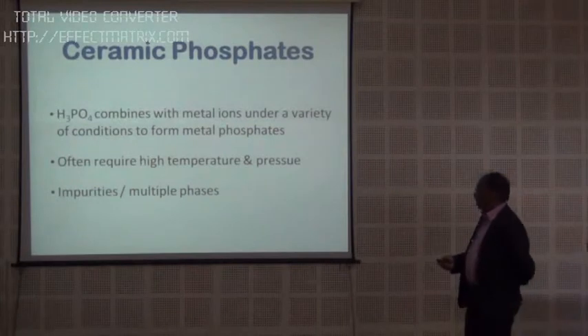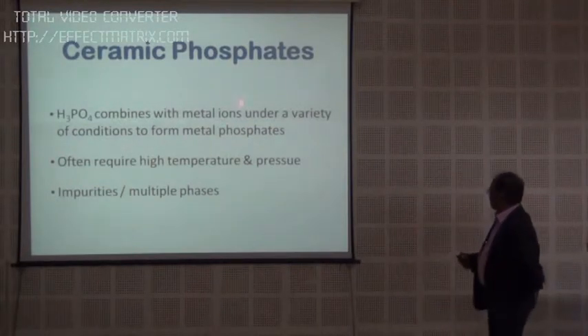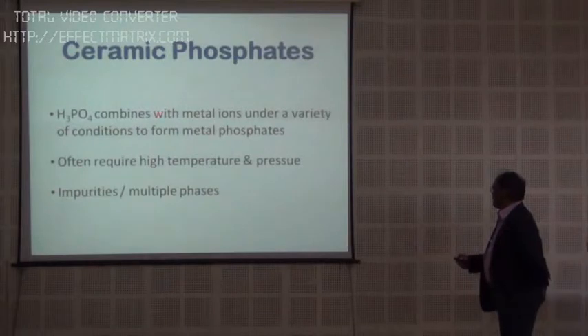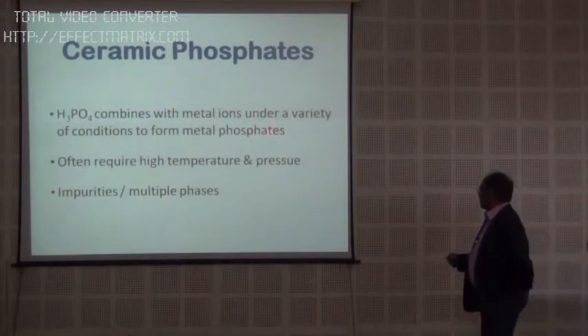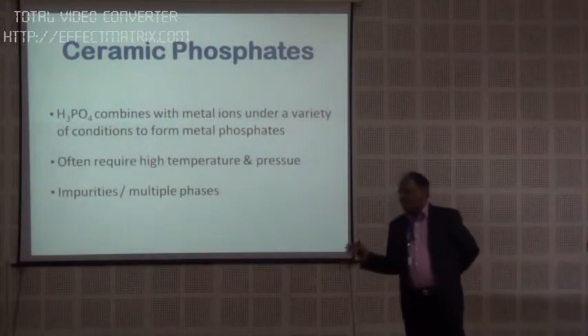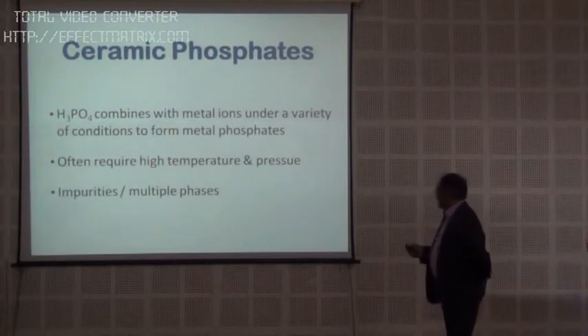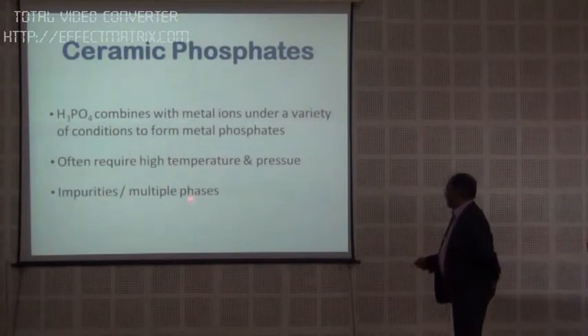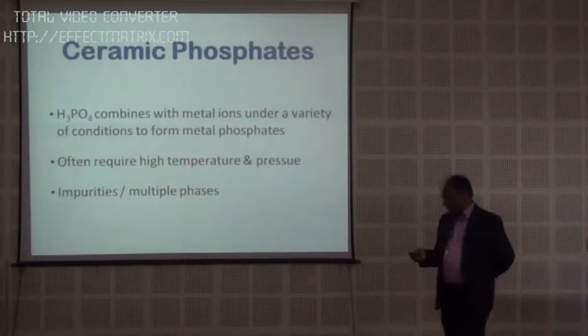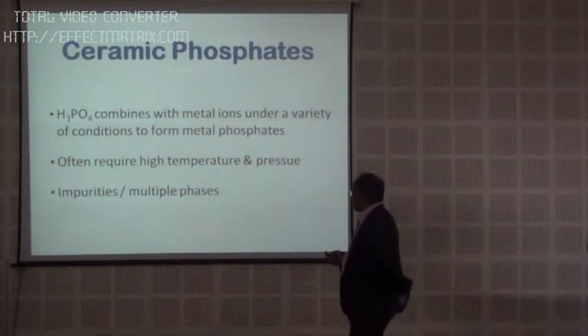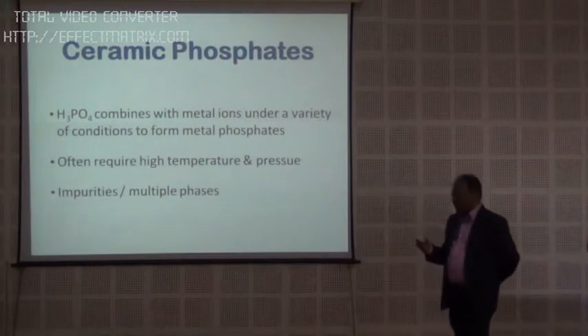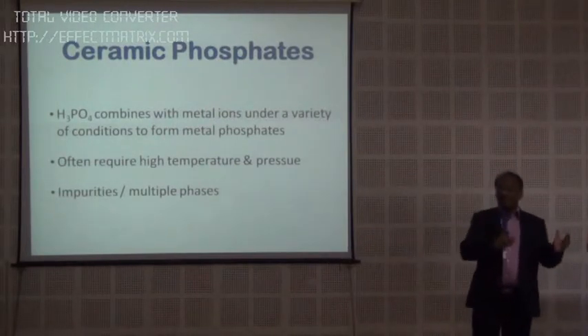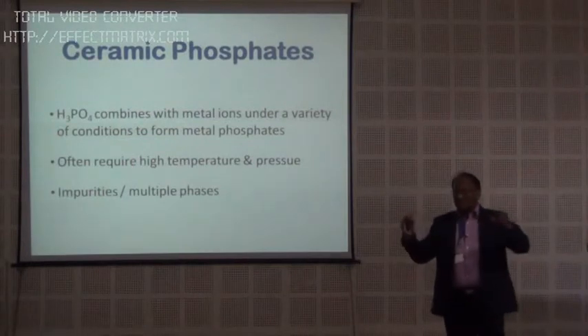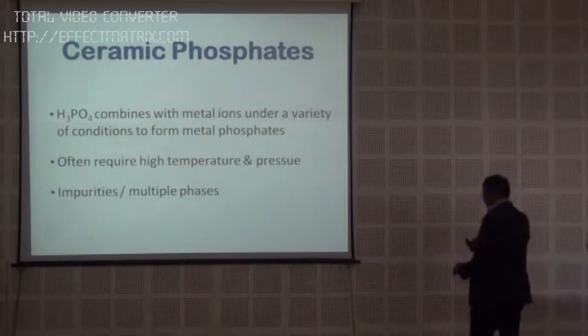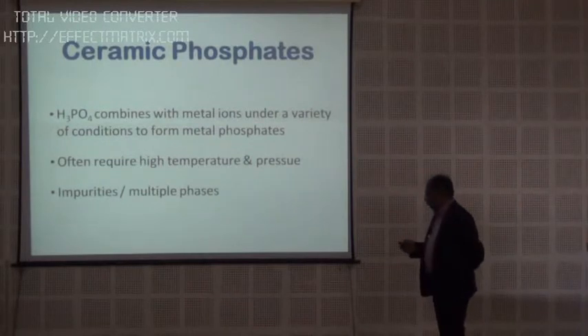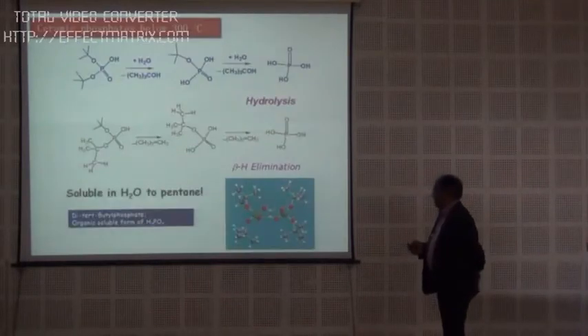Phosphoric acid, for example, combines with a large number of metal ions. In fact, every element in the periodic table, under a variety of conditions, forms metal phosphates. They have an enormous number of applications which I'm not going to catalog, other than to say that much of this high temperature synthesis spits out materials which are often impure and contain more than one phase, because phosphoric acid forms pyrophosphoric acid, metaphosphoric acid. So all these happen at high temperatures, so you get a number of phases. So often phase pure materials are very rare.